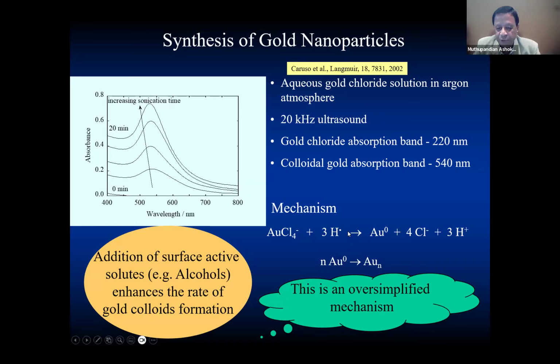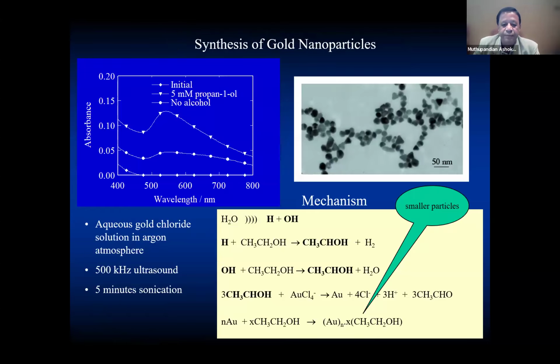So how are these nanoparticles produced? As I already told you, if I have water, water decomposes within the bubble to form hydrogen atom. The hydrogen atom can then diffuse out of the bubble and react with the gold ion. Gold ion has an oxidation state of 3+, so 3 hydrogen atoms will provide 3 electrons to the gold ion to form a gold atom. The gold atom then can agglomerate to form gold nanoparticles. It's a very simplified mechanism. Okay, so you can use 20 kilohertz or higher frequencies. I'll quickly highlight the frequency effect in the next slide.